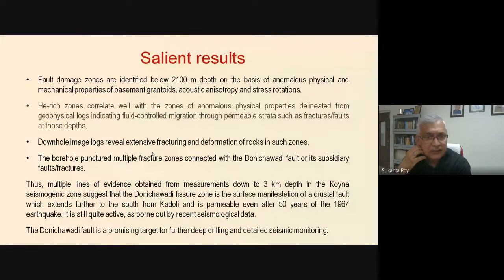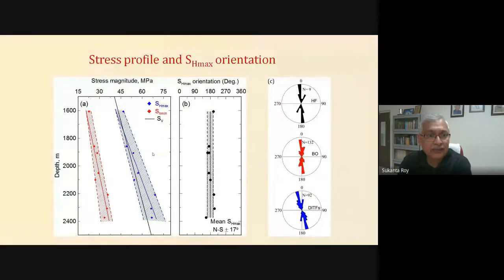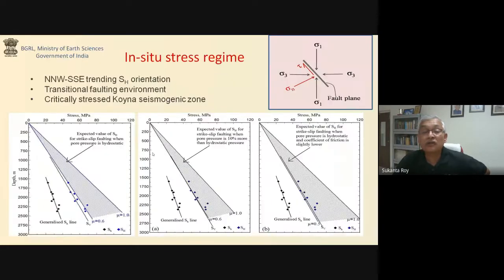So I'll skip this. I already spoke of this. Now, quickly, I'll go into the stress profile because we were able to measure directly the stress magnitudes here using hydrofrac tests up to 2,500 meters depth. This is one of the deepest direct stress measurements in the crystalline basement anywhere. As you can see on the right hand panel, we have the stress orientations from hydrofrac. Then shown in red is the stress orientation that we got from the breakout analysis, and the last one in blue shows the stress orientations from the drilling induced tensile fractures. And you can see that they are relatively consistent, almost north-south orientation.